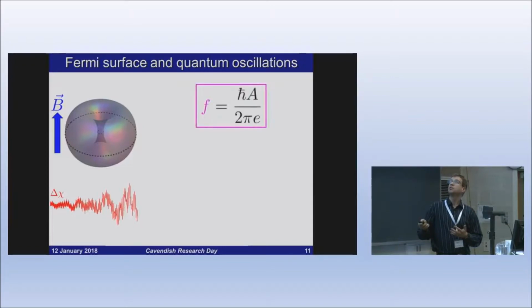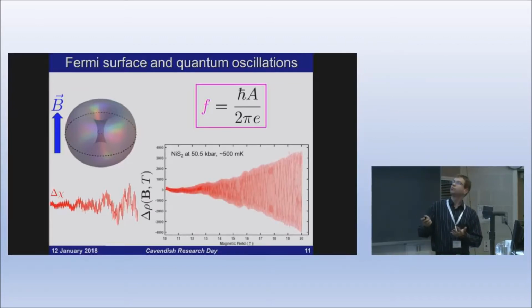And these oscillations are periodic in 1 over the magnetic field, and the frequency is proportional to the area of the extremal cross-sections. For this donut here, there is this inner orbit and the outer. And by adjusting the direction of the magnetic field, we can map out the shape and size of the Fermi surface. And this would be a typical signal, like I'll show later, for nickel disulfide for resistivity.